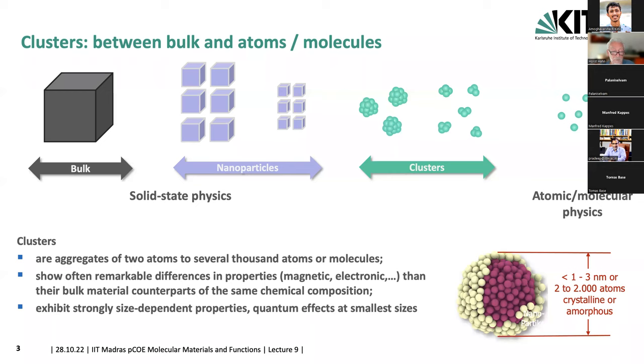But in general, clusters are aggregates of two atoms to a few thousand atoms or molecules, and they often show remarkable differences in properties, magnetic, electronic, optical properties, from the bulk material counterparts, which are of the same chemical composition. And in addition, you can change the properties by changing the size. So they show very strong size-dependent properties. And then at the smallest sizes, in many cases, you also see quantum effects.